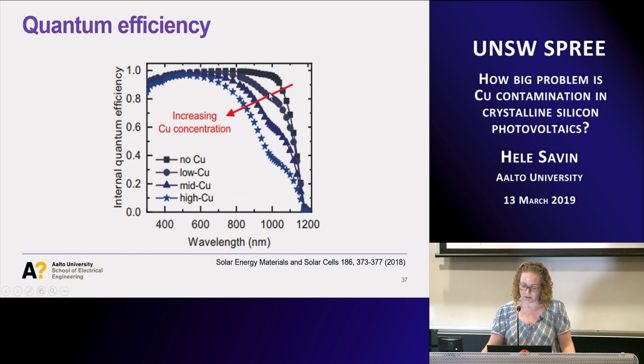So there's a clear trend towards really low efficiencies the higher your copper concentration becomes. So even these low concentrations can cause some very severe degradation. So this would be the initial curve, and then how it really goes back. I guess you all have the expertise to interpret this quantum efficiency curve. But in efficiency you can already guess how big the losses we are talking about are after seeing these.